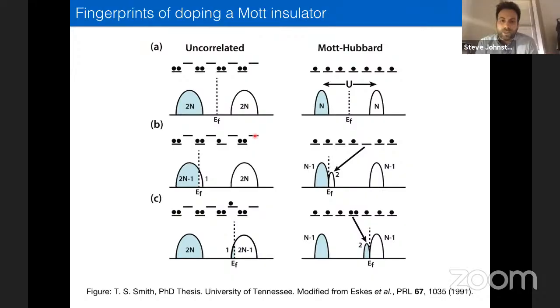Yeah, so the problem with that in this system is that when you raise the temperature, the atoms actually start to disassociate from the surface before you reach the temperature scale of the Mott transition. Oh, I see. Okay. And so doing it with temperature is not really a good way to go about it in this particular system. Okay. And it just has to do with the chemistry of the surface. Yeah. I see. Thank you.